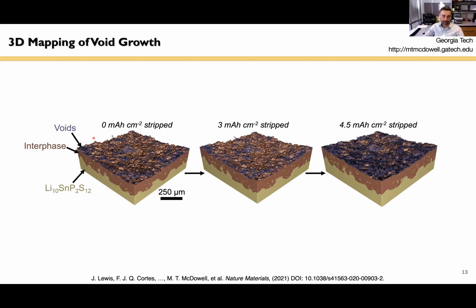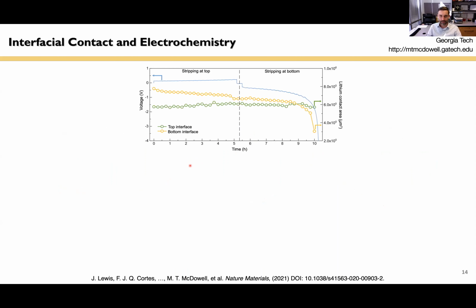So at the beginning of the experiment, we do have quite a few voids actually, because our interfaces were imperfect. But as we strip the lithium, you can see stripping quite a bit of lithium, not much really changes. But then at the end of the experiment, we stripped 4.5 milliamp hours per centimeter squared. And you can see that there's just a ton of voids that have grown in at the interface. We've lost contact substantially across the interface. So this is one way of looking at it, nice 3D reconstructions. That's pretty. I think this is potentially a more useful way.